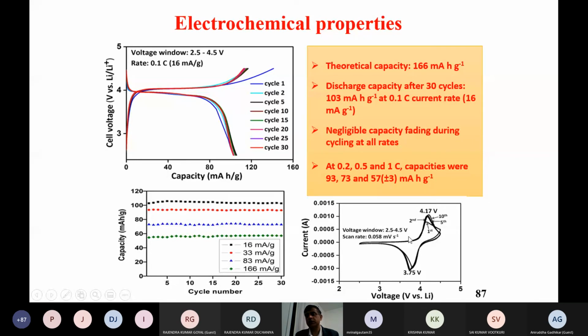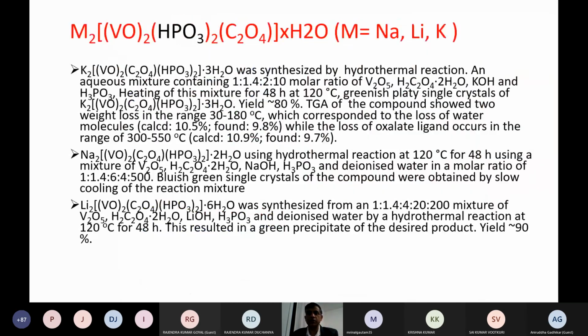And usually for any battery or cathode, they are looking for a good reversible redox potential, meaning positive current, negative current, which clearly indicates that this material will be really useful. Although sometimes theoretically it is 166, although we can calculate theoretical capacity, we are not able to get near theoretical capacity. Sometimes that's a big problem. For any new materials we make, we can calculate theoretical capacity, but practically we will not get that much capacity.